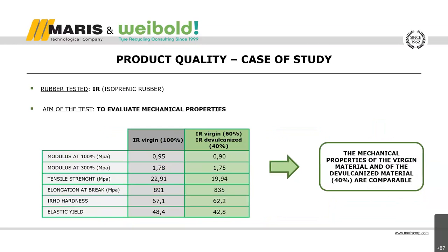Now I'm going to conclude this section giving you the results in terms of mechanical properties, such as modulus, tensile strength, elongation at break, and hardness, comparing the virgin rubber and the devulcanized mixture. As you can easily see in the table below, the mechanical properties of the virgin material and the mixture with 40% devulcanized material are comparable.